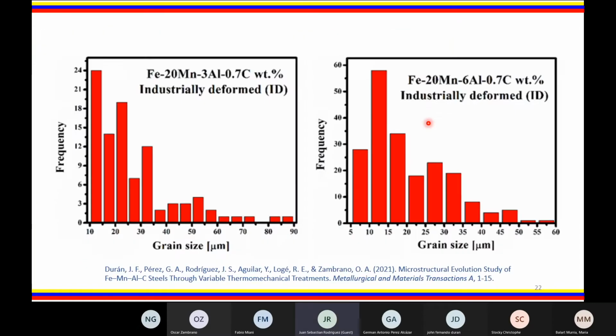As the aforementioned is presented in this bar graph, it is observed that there is a process of formation and growth of grain during the 3-step processing, in which a structure of small, randomly oriented grains is obtained.